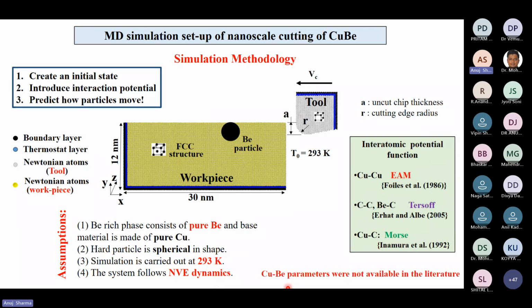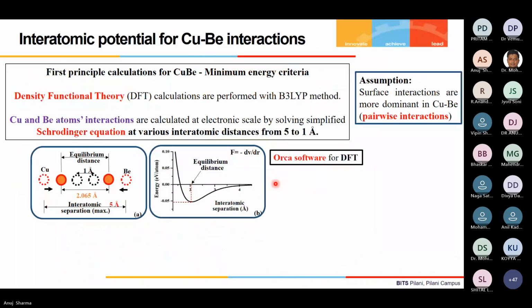Here the thing was that the copper beryllium parameters for this interaction potential energy function were not available in the literature. So for that, I applied the first principles calculation, which is a quantum simulation based approach, to evaluate the parameters for the interatomic potential. I took two atoms, copper and beryllium, and their distances were changed. Based on this quantum mechanical effect, initially, when the two atoms were far away, there was some weak attraction. When they were brought closer, the attraction became stronger. And once they were brought even closer, past this equilibrium distance, some repulsion was shown.